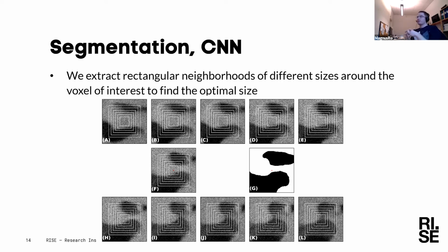But that was also a reason we needed to do manual annotation, because basic thresholding and filtering gives us nothing here. Very poor performance, just because the overlap of the intensities is considerable. But you can envision it as dark regions being pores and bright regions being material.